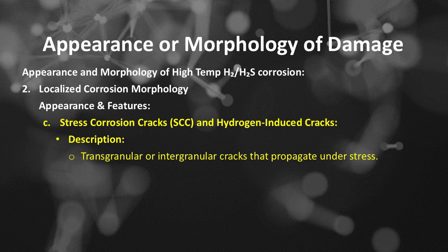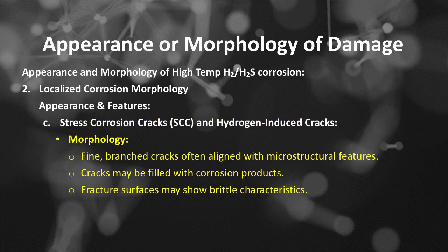The number C of the appearance and features of localized corrosion is stress corrosion cracks, SCC, and hydrogen-induced cracks. Transgranular or intergranular cracks that propagate under stress. The morphology of stress corrosion cracks, SCC, and hydrogen-induced cracks: fine, branched cracks often aligned with microstructural features. Cracks may be filled with corrosion products. Fracture surfaces may show brittle characteristics.